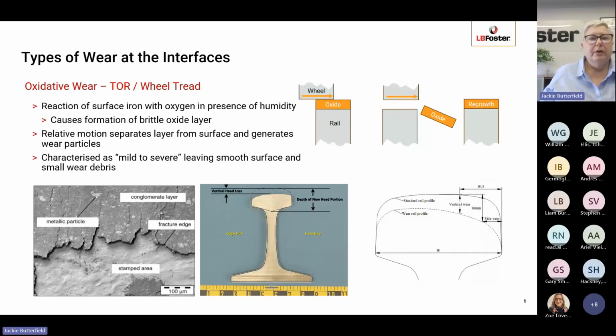So the second type of wear I'm going to look at is oxidative wear. And this is typically associated with the top of rail and headwear or wheel tread wear. Not exclusively, you can have multiple different types of wear mechanisms in each of the areas on the wheel and the rail, but oxidative wear is particularly associated with top of rail. So rail steels are high carbon steels. They are not particularly corrosion resistant, and so they will readily oxidize in the presence of oxygen and air and other oxidizing agents and chemicals. So in air, obviously, most railways are outdoors and there will be oxygen there, otherwise the passengers wouldn't be able to breathe. So you will have an oxidation of the surface of the rail.